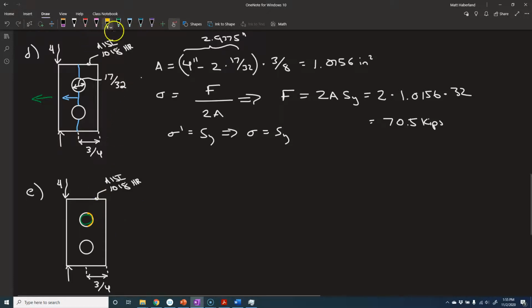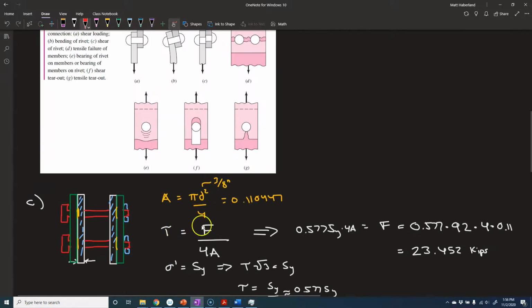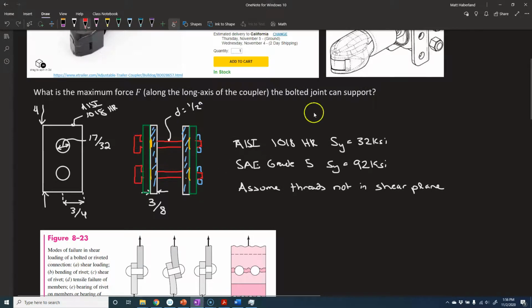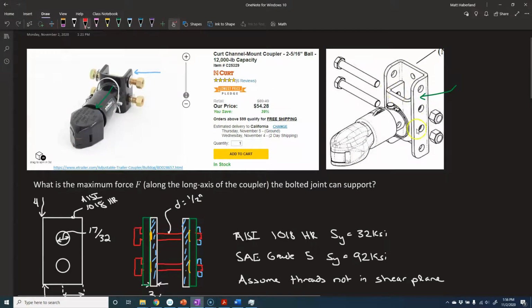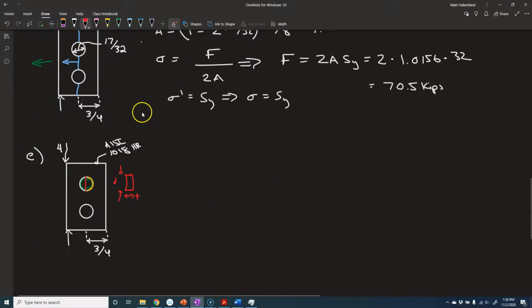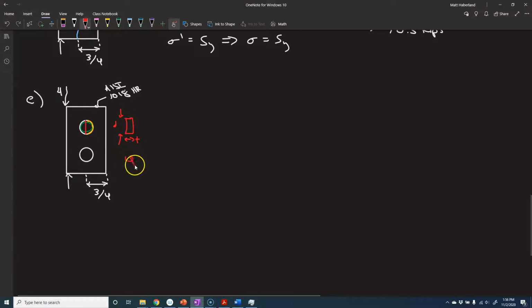But as a matter of convention, what we do is we look at the projected area. So we look at this area. And when you look at it from this direction, you see an area that is the diameter of the hole, that's this distance, times the thickness of the part. Part here is 3/8. I'll label it T for thickness. We've got 4 of those interfaces where there's going to be that bearing stress. 1, 2 from the side view, but you've got to keep in mind we've got 2 of these things. We've got 4 holes, 2, 3, 4, that are going to be under that bearing load, and we're going to assume that the load is handled equally among them, so just keep that in mind.